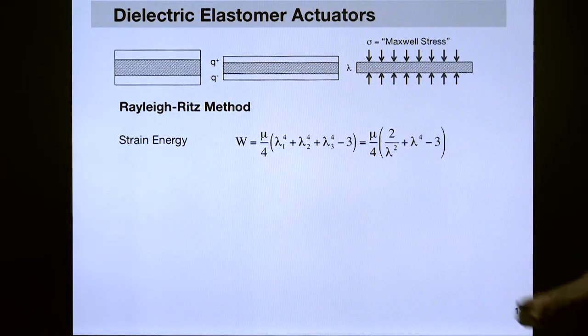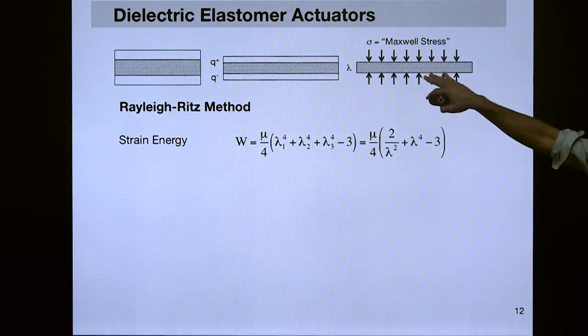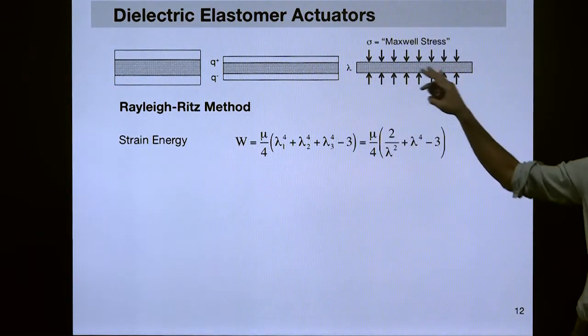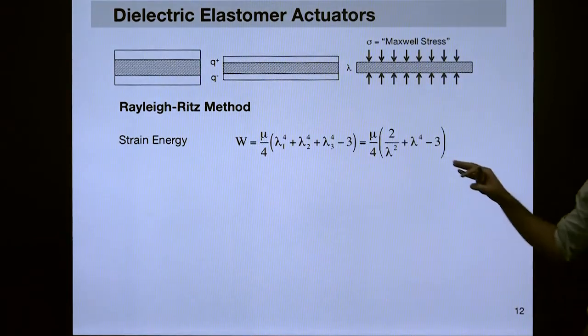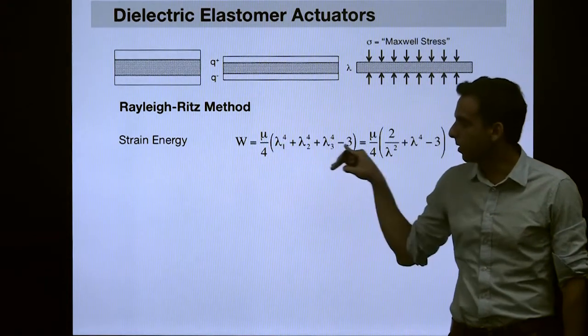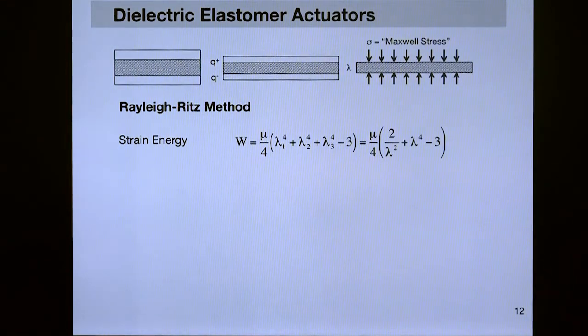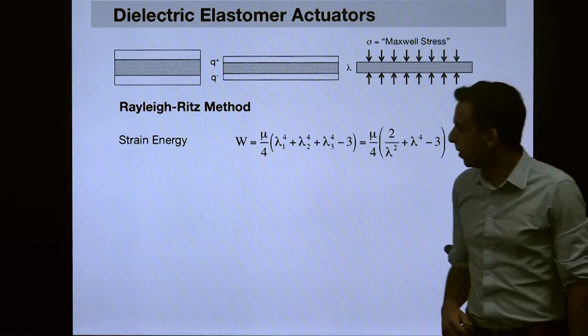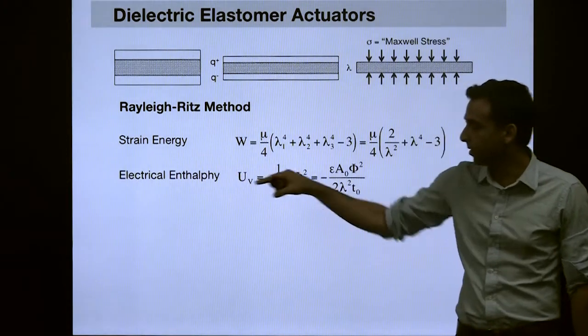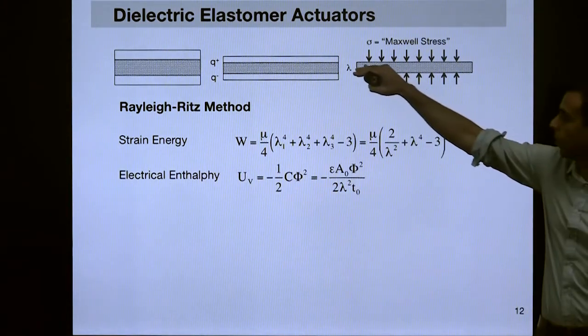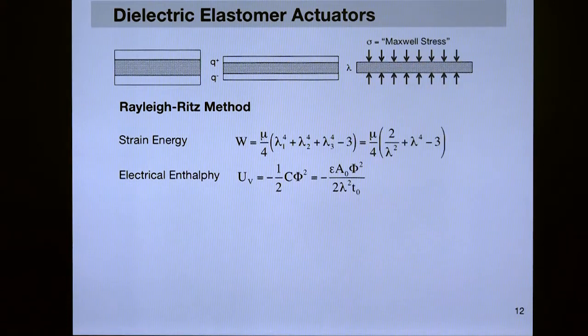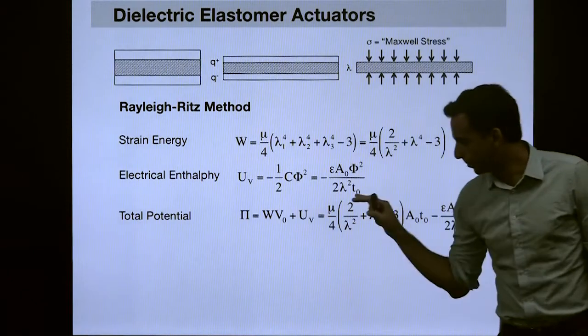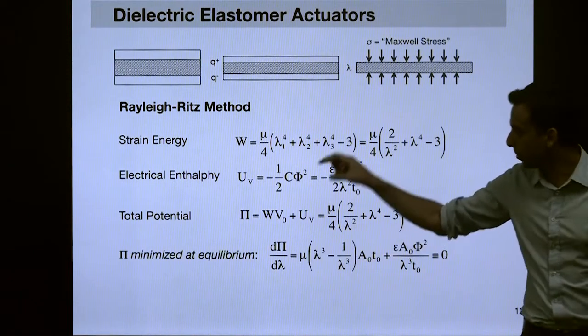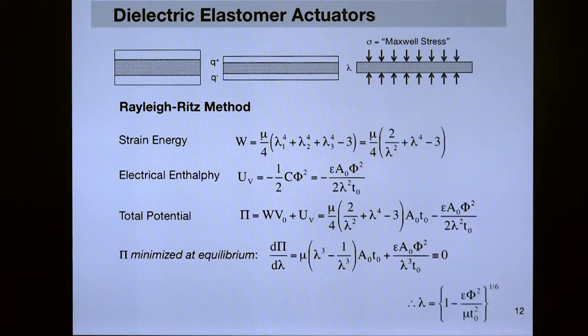In this case, one source of potential energy, of course, is the elastic strain energy. We can use any nonlinear constitutive model to represent what that stored strain energy is. Here, I found that for these materials, a fourth order Ogden model is the most relevant because it exhibits this strain stiffening effect when we go to much larger stretches. So that's one contribution. The other is the electrical enthalpy associated with all the electrostatic charge on these two surfaces. So we add them up, take the total potential energy, and minimize with respect to our free variable, which in this case is the thickness, and then we get our scaling relationship between thickness and applied voltage.